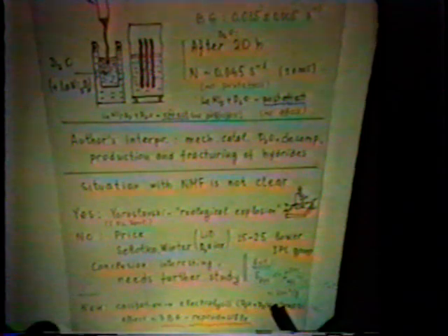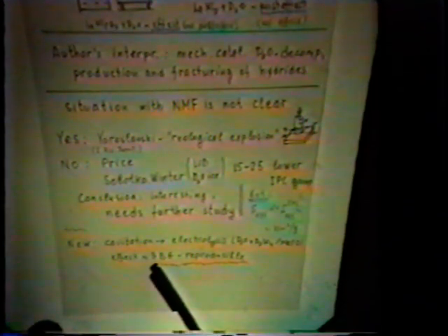Just before this conference, I was informed by this group that they continue their cavitation measurements. This time, after cavitation, they used the titanium vibrator as a cathode for electrolysis of heavy water. And in this case, they observed an effect which is about 3 times the background level. And this effect is highly reproducible. Well, the next topic is nuclear chemofusion.